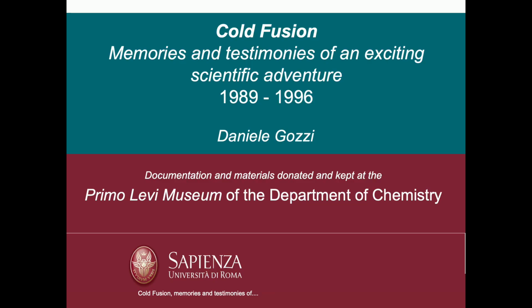The most relevant result, but not the only one that emerges, above all because by its nature it's free from any conceivable artifact, is that an X-ray film was impressed, in a very singular way, during the electrolysis of an alkaline water solution with a palladium cathode. Under the same conditions, with a platinum cathode, the same film was not exposed. It should be emphasized that this occurred while the system was producing excess heat only in the cell with the palladium cathode. To impress a film of that type requires a radiation with energy about 3 orders of magnitude higher than the energy necessary to sustain the electrolysis of water, even if it was heavy water.